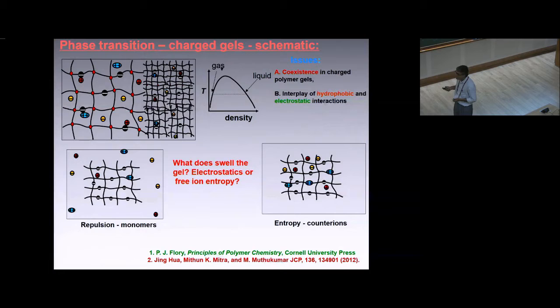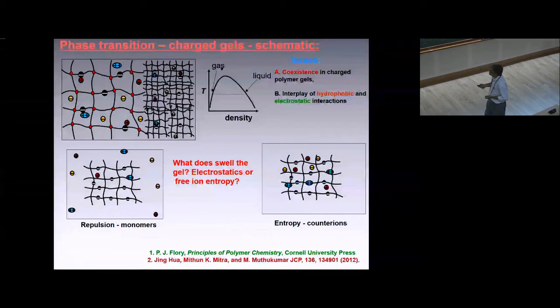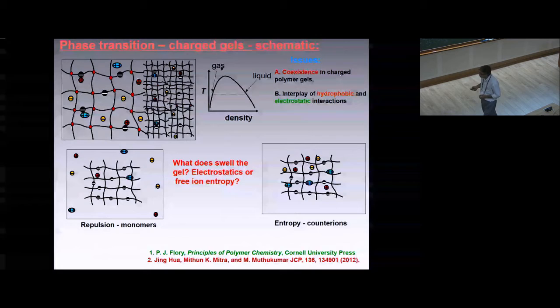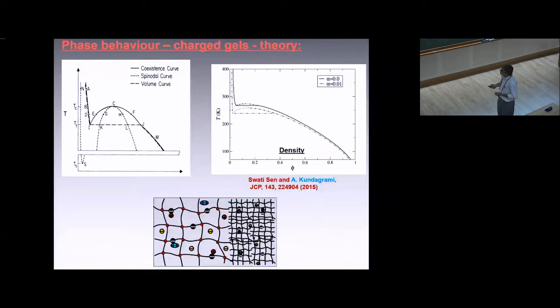This is an equilibrium feature. Regarding swelling of the gel, one can think of the role of electrostatic charge repulsion and free ion entropy. Free ion entropy in the sense that the gel must remain electroneutral during the entire process, and free counter ions like to enjoy more volume, so the gel can swell in addition to charge repulsion of monomers. The question is what are the more important effects here.